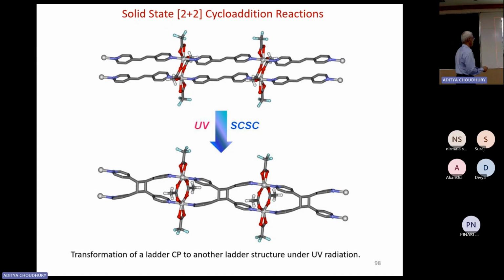When you put this compound under UV light, it may be sunlight, or a mercury lamp, or whatever special UV lamp you have got, it undergoes photoreaction. You get this product. It's colorless, and it changes to a very light yellowish or creamish color, still maintaining the transparency. When you determine the crystal structure, you see that it's all chemically transformed.